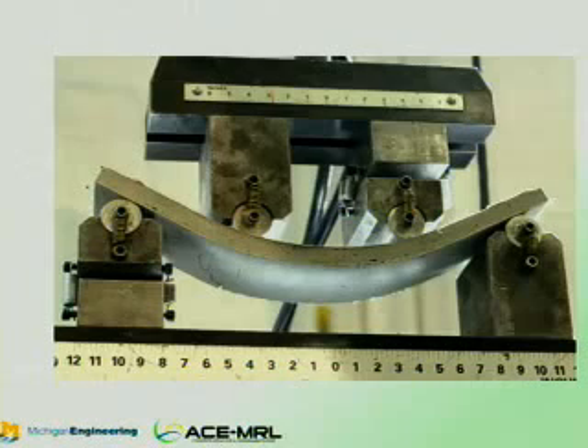ECC has a tight crack width, about 50 microns in diameter, due to fiber bridging. These cracks may heal themselves at the surface by hydration and carbonation through wetting and drying, reducing maintenance costs in the field and improving durability. This is a picture of an ECC coupon subjected to flexural bending. As you can see, ECC can withstand more strain before failure than normal concrete.